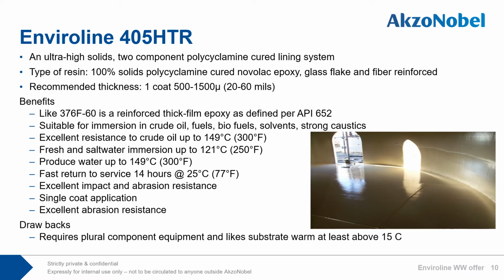Excellent resistance to crude oil up to 149 C, fresh and saltwater immersion up to 121 C, produced water up to 149 C, fast return to service 14 hours at 25 C, excellent impact and abrasion resistance, single coat application. Drawbacks are it requires plural component equipment and likes the substrate warm, at least above 15 C.